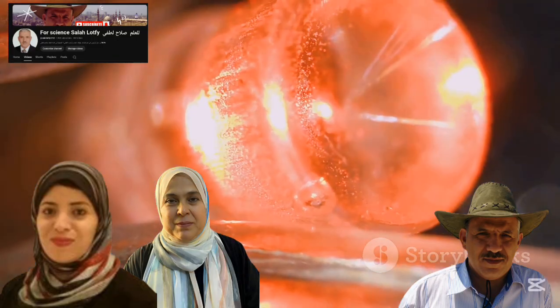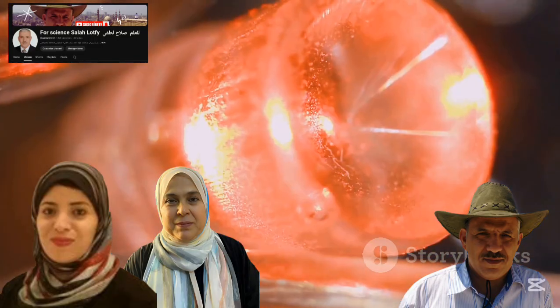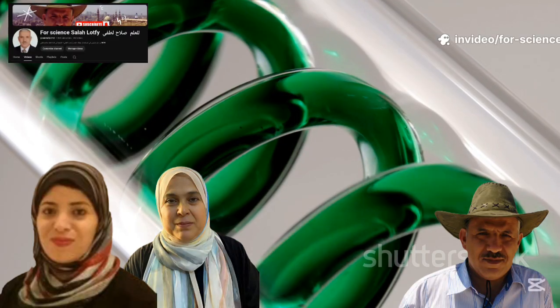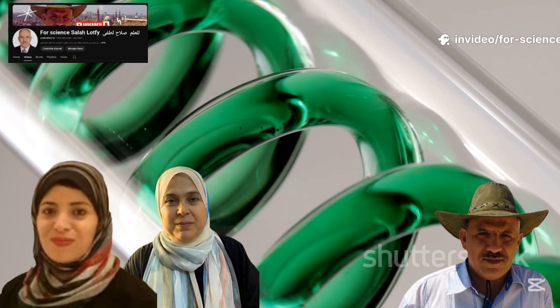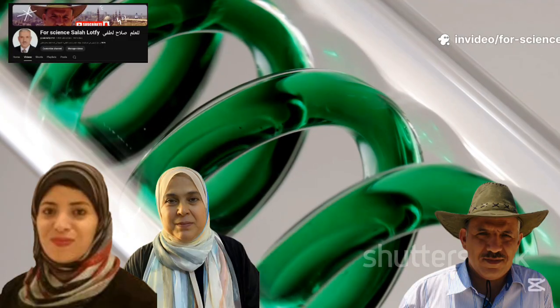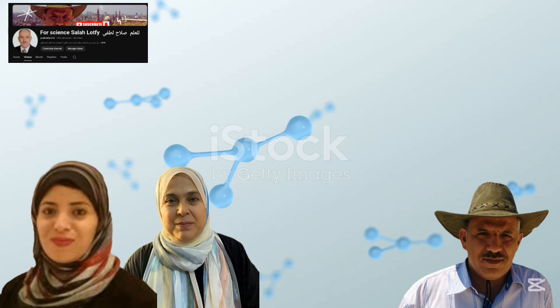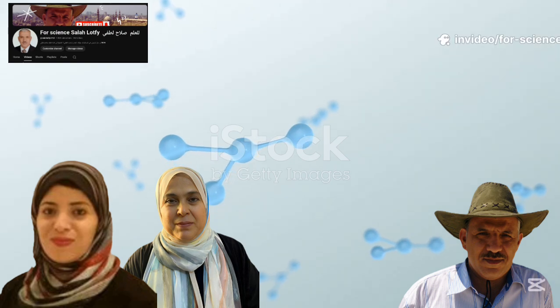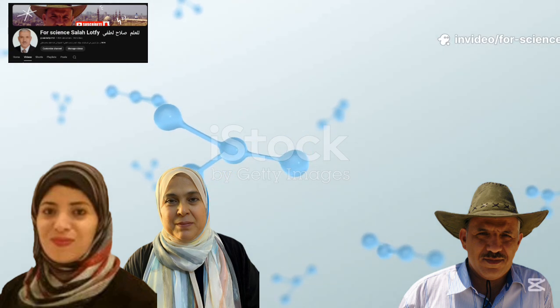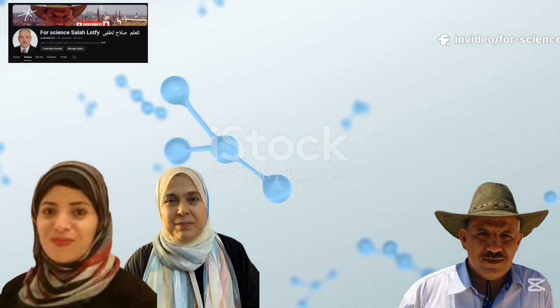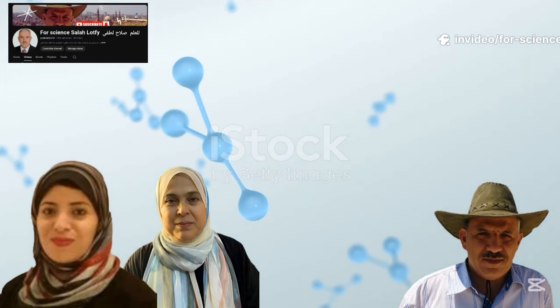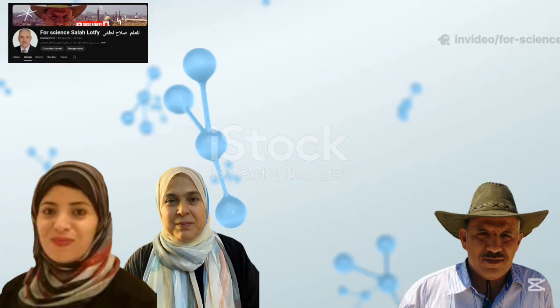Ce-doped glass benefited from cerium's ability to absorb radiation photons and stabilize defects. SB-doped glass showed stability thanks to the massive polarizable Sb3+ ions, which slow down liberated electrons. Mn-doped glass relied on transition metal ions and compacted AlO4 groups to capture defect centers. The disappearance of certain BOH bands after irradiation confirmed stronger BOB linkages, proving that these glasses actually become more compact and stable under radiation stress.